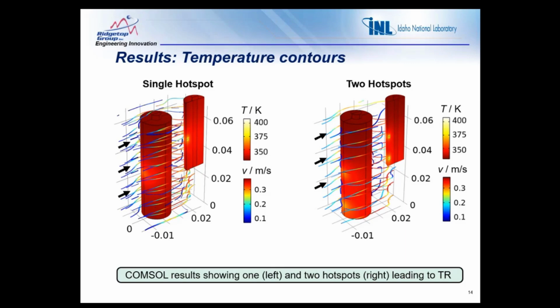For the single hotspot case on the left, we see the temperature contour and the air flow lines demonstrate the cooling effect. But as shown in the slide cross section, the maximum temperature is concentrated at the hotspot. This is where the thermal runaway propagation begins. This localized heating is critical as it drives the initiation of thermal runaway.